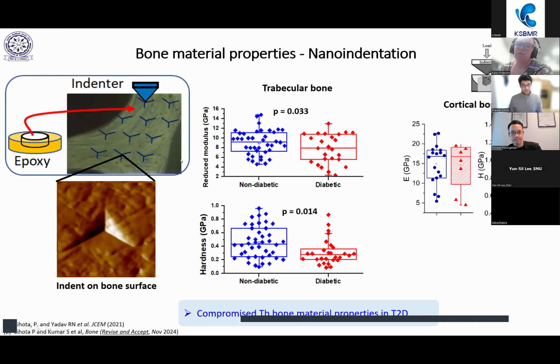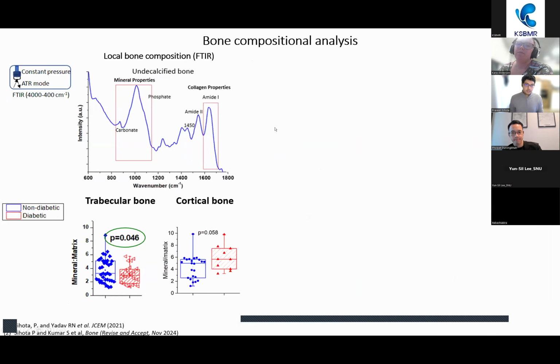Material property has been investigated for both trabecular and cortical bone. We found lower material property in the diabetes group for trabecular bone, whereas in cortical bone, there is no significant difference in material property. Next, bone compositional analysis with the spectroscopic technique. A standard parameter is the mineral to matrix ratio, which is the relative mineral to matrix content. It is lower in trabecular bone, whereas in cortical bone, the mineral to matrix ratio is not significantly different.